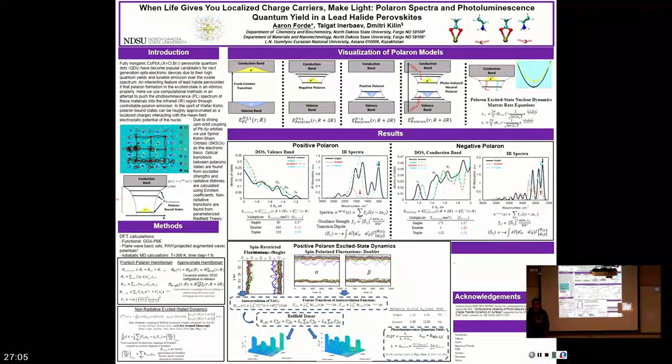I guess I'm just going to have to work on describing the couplings and the parameters in them a little bit better, but we don't have to go too in depth because we're going to approximate them using Kohn-Sham DFT. So we assume that for our electronic and nuclear energies, we can just use the adiabatic states for our ground state method, and then to approximate the polaron formation, we add an additional charge and let the model optimize around that charge.